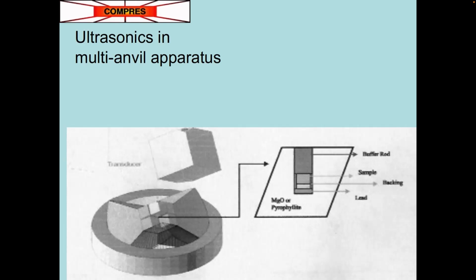showed you the massive apparatus at ASU in his introduction, it compresses these cubes. On the back of one of the cubes, we mount a transducer, and that transducer generates an acoustic wave that travels through a buffer rod. At the interface with the sample, it has an echo. It travels through the sample, generates another echo, and the difference of those two, of course, is the travel time within the sample. Still no measurement of length directly, but it allowed these experiments to be done at pressures up to 5 to 10 GPa.